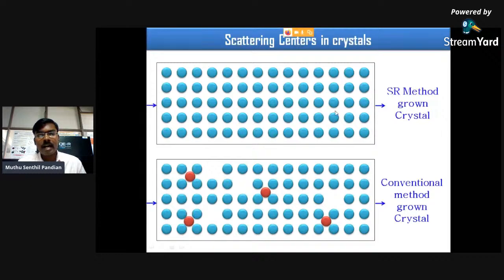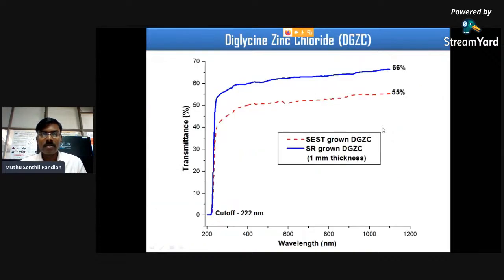So there is a higher output intensity, but in the case of the conventional method grown crystal, due to scattering centers, the output intensity is less compared to the SR grown crystal. The UV-Vis-NIR transmittance value of the SR grown diglycine zinc chloride crystal is 66%, but in the case of the conventional crystal, the output intensity is less because of the scattering centers, at 55%. UV is a transmittance measurement.